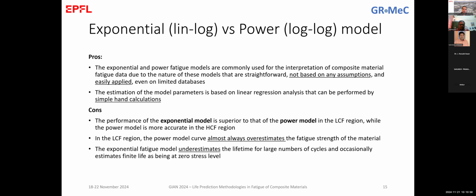some problems when we see them on the plot, because the power model, because it is a power exponential equation, the power model tends to overestimate the life at very low cycle fatigue, where the exponential model has problems when it goes to the high cycle fatigue, because it's a straight line. And you imagine that if you continue with this straight line, at a certain point, with the model, you will claim that the material will fail at a certain large number of cycles, but will fail even under zero stress, which of course physically it's not possible.